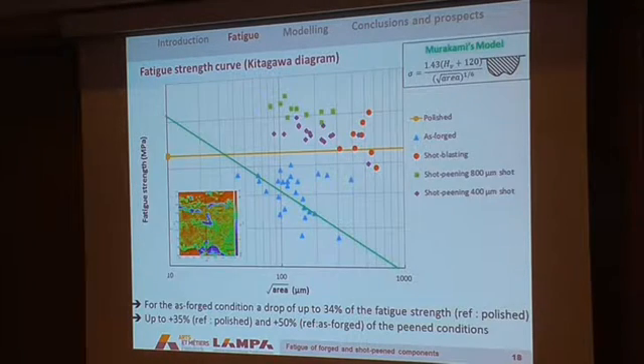Now, if I try to draw for all our conditions a Kitagawa diagram, with the fatigue strength as a function of the square root of area, you get that kind of points, where you've got the polished reference here. For the as-forged conditions, you see here the effect of the defect size. You observe a blue scatter here. And for the shot blasting and the two conditions of shot peening, you see also the effect of the defect size.